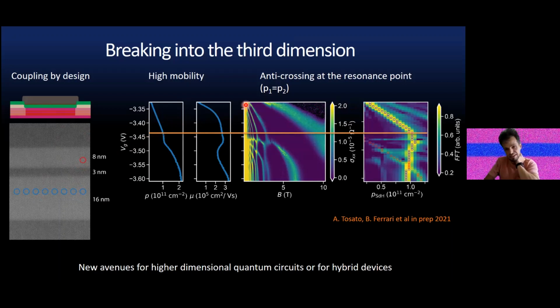and here the fan diagram goes from a typical fan diagram of a single quantum well to a more complex pattern. And beautifully, here in the Fourier transform, you see that this is nothing more than the density of the bands from Shubnikov-de Haas, how this really nice linear increase is due to the bottom quantum well that is populating. Now, as you are increasing further, you're increasing the density of the top quantum well, keeping the other one constant in first approximation. So here you see all the signatures of this story.